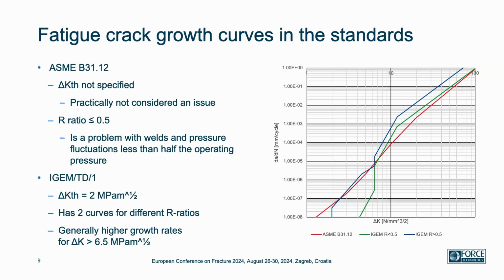These curves have then been used in the standards, and now I've taken three curves from two standards, and the ASME curve is the red one shown over here. If you look into the ASME B31.12 standard, the threshold value is not specifically designed in that curve, so it continues down this way, but practically it has not been an issue in the assessments that we have conducted.